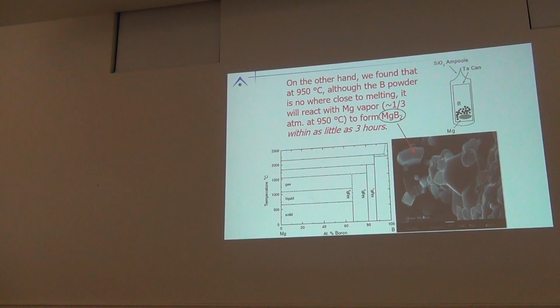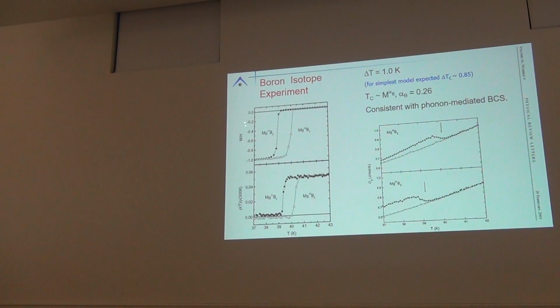This is the good stuff. Okay? Now, with that, we were able to take high purity isotopic boron, boron 10, boron 11. We see an isotope shift. It's a huge isotope shift. It's 1 Kelvin. Okay? We can see it in magnetization, in resistivity, in specific heat. This is the first published paper on superconductivity in MgB2. And with this first paper, we made it clear this was an electron-phonon mediated superconductor.